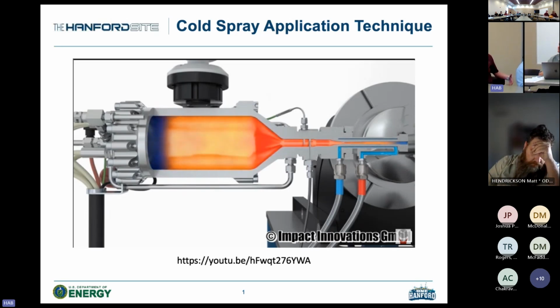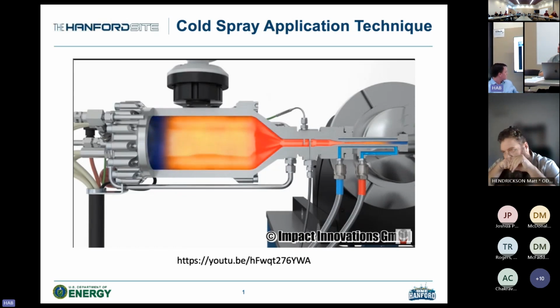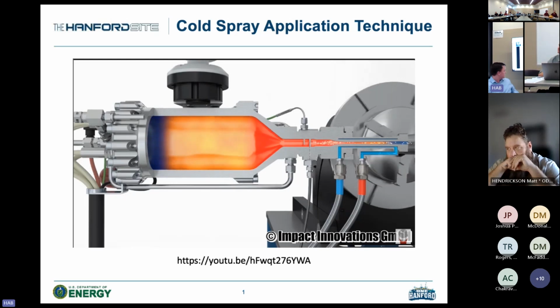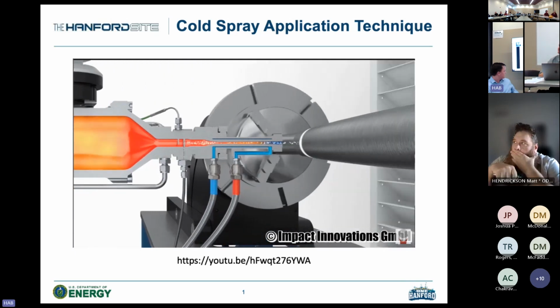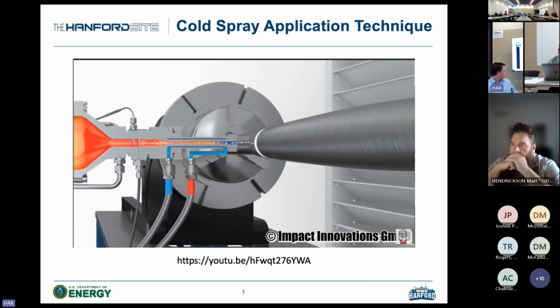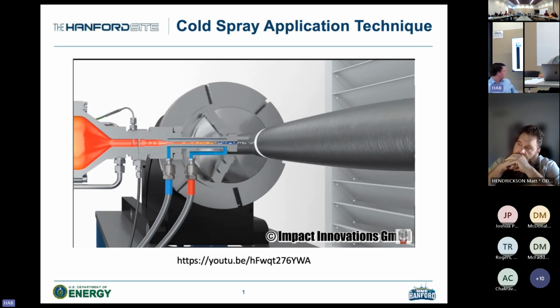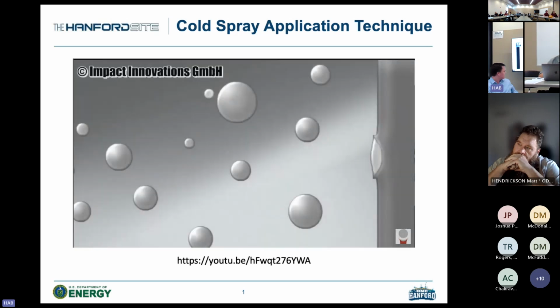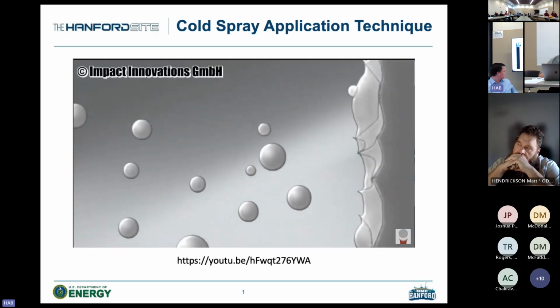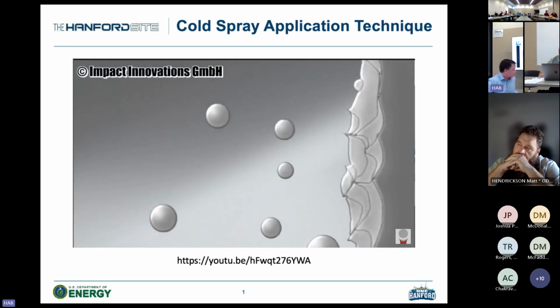The cold spray process starts by heating up a pressurized gas. In our case, we are heating up nitrogen gas to 650 degrees Celsius. Once that desired temperature is reached, metal powder particles are introduced into the spray nozzle and they exit at supersonic speed. The cold spray coating is formed through ballistic impingement of those materials onto the substrate.